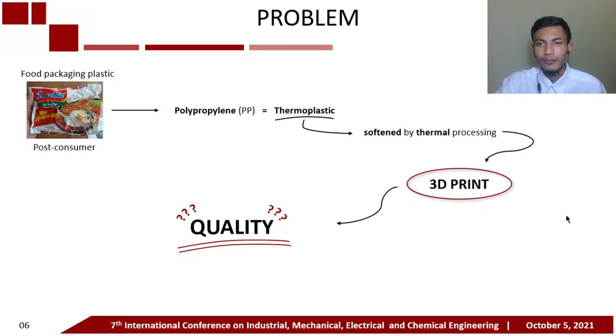printing techniques and choose the industrial standard polypropylene or PP and polylactic acid or PLA filaments as benchmarks, by setting the 3D printer's nozzle temperature as the independent variable, and I set the temperature variations to 180, 190, 200, 210, and 220 Celsius.